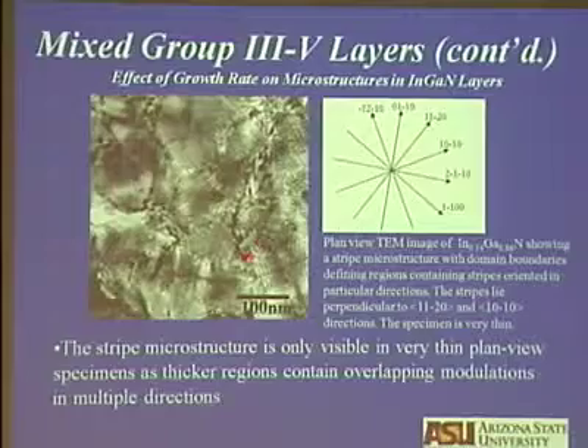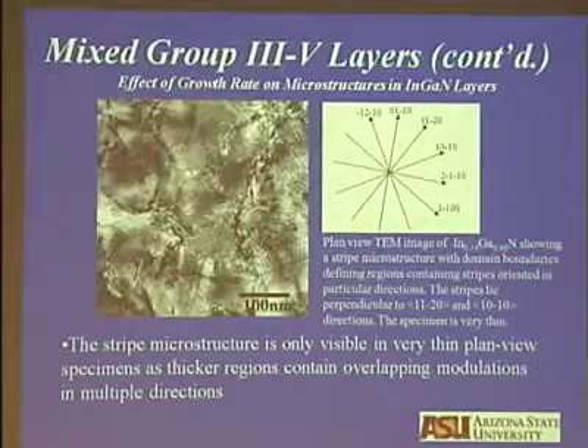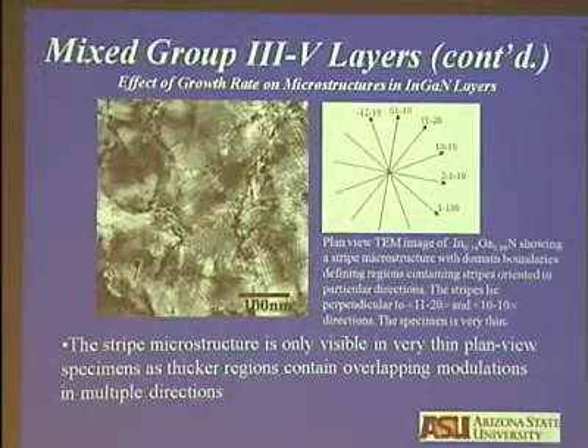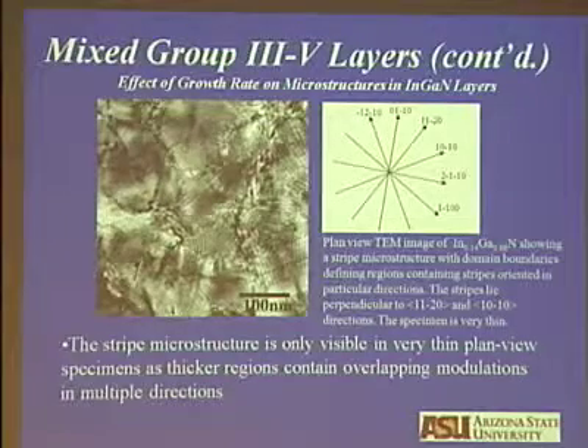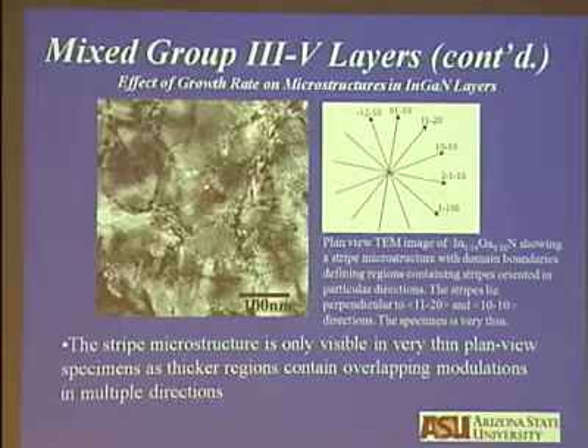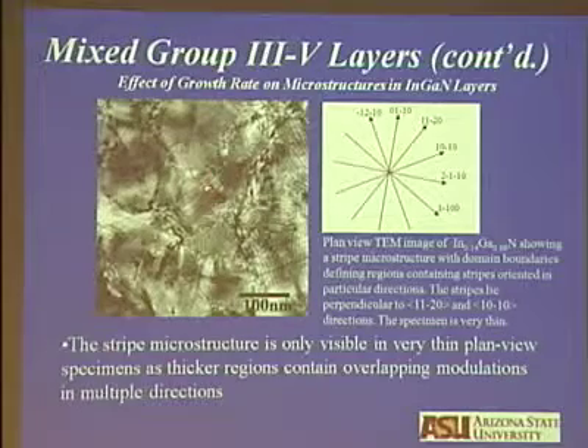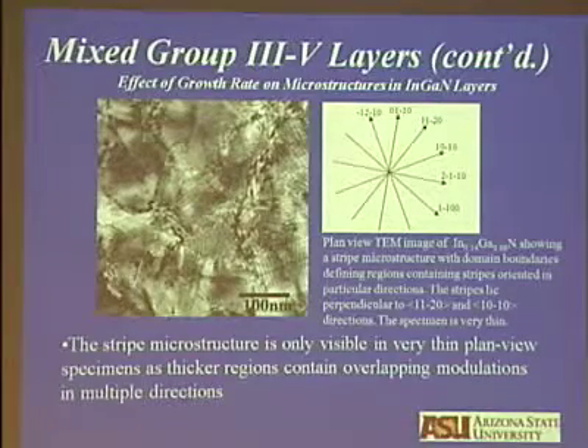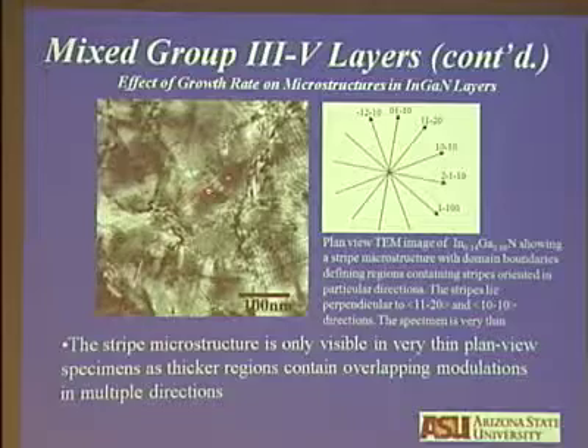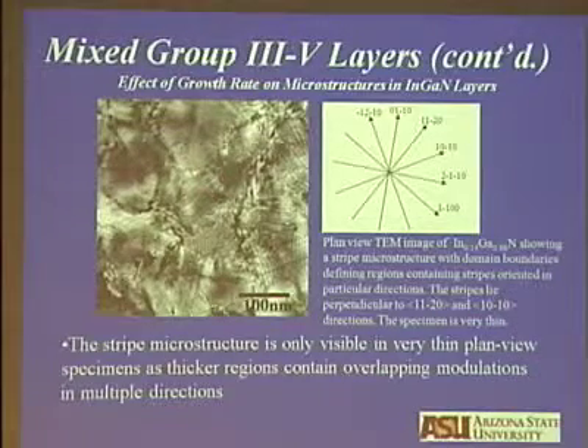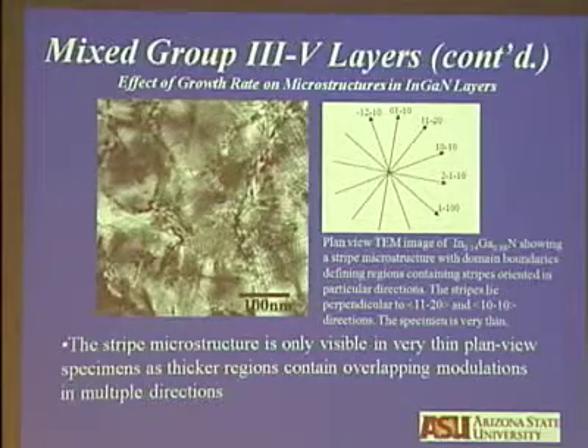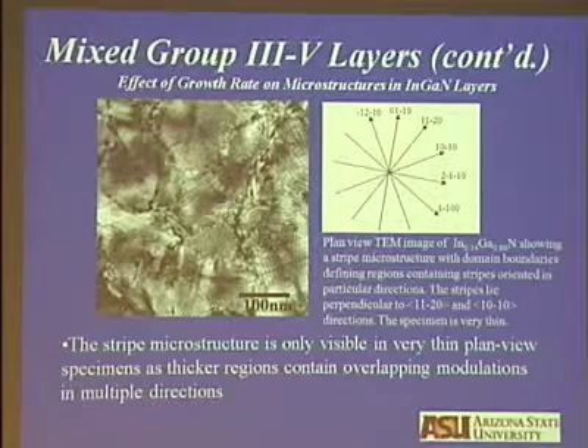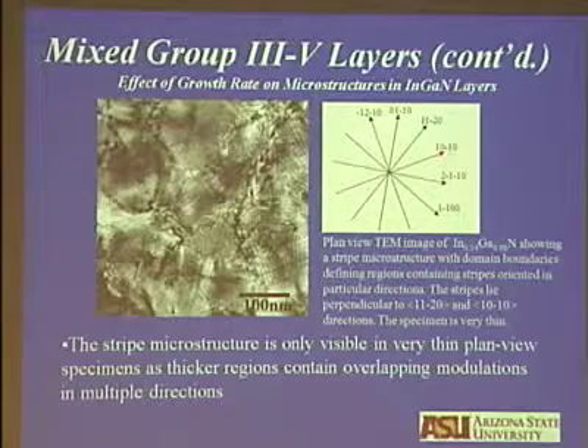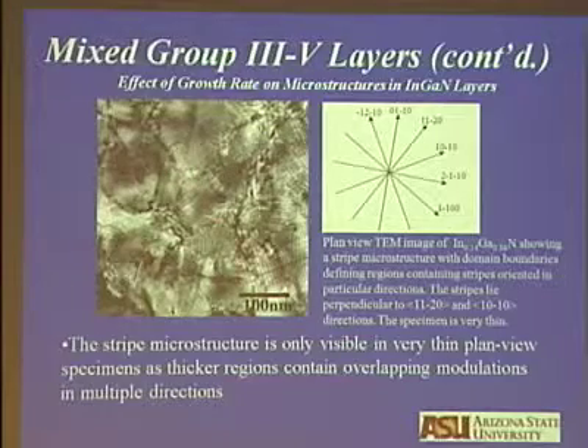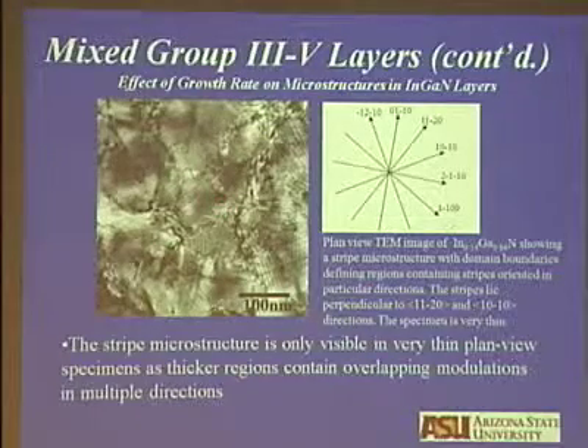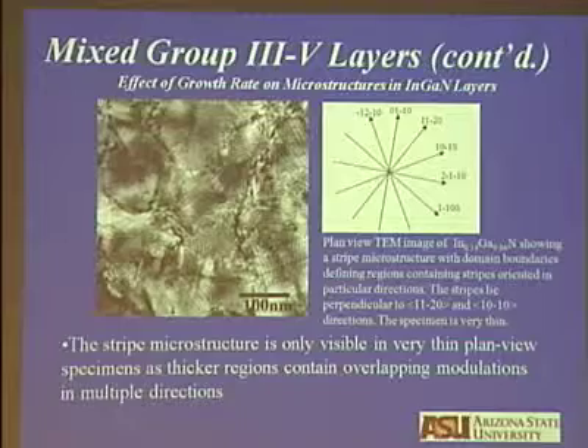This layer was grown at a much higher growth rate. There was a reason why we did that. We will try to understand why they are ordered. And you see the dark stripes are indium-rich. We haven't proven it. Dark stripes are indium-rich regions, and the light stripes are gallium-rich regions. And if you look at it, the volume fraction fits very well. And also look at the crystallography. The directions normal to these stripes tend to lie along one of these directions.